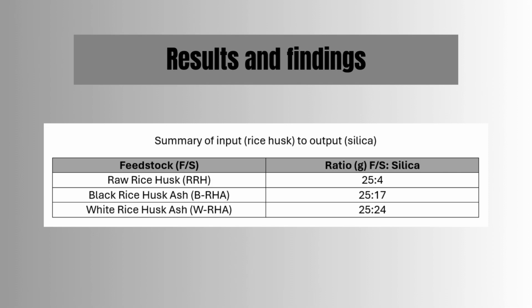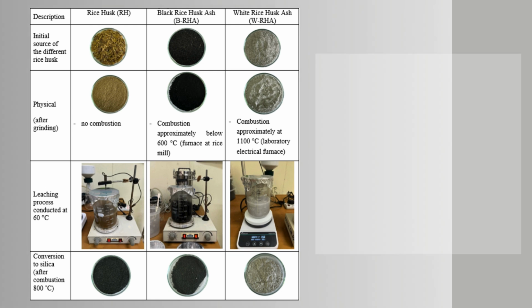Next to the results and findings part. This is the summary table of input rice husk to output silica. There are three different feedstocks. For raw rice husk, we are able to obtain 4 gram of silica from 25 gram of feedstock. For black rice husk ash it is 17 gram, and for white rice husk ash it is the highest, which is 24 gram.